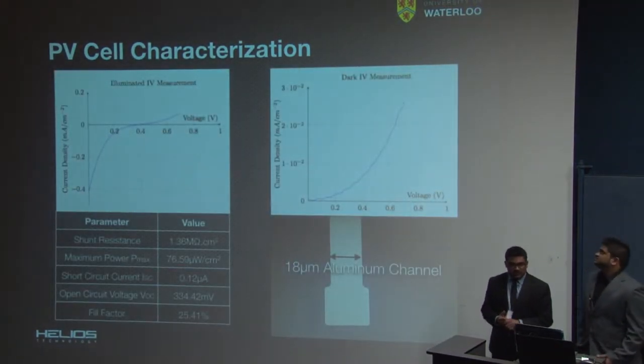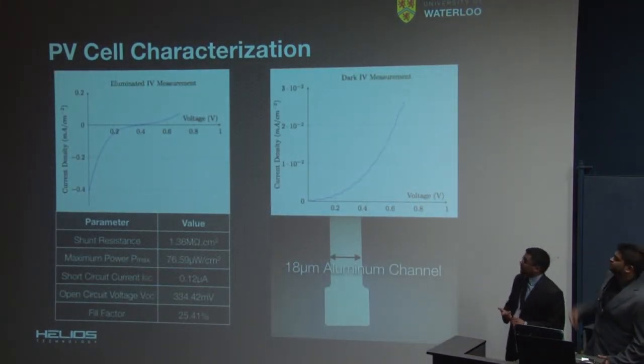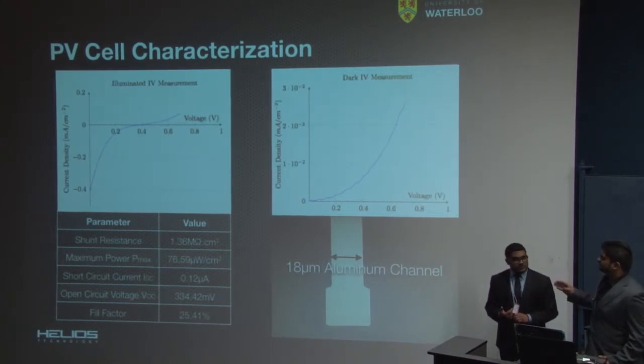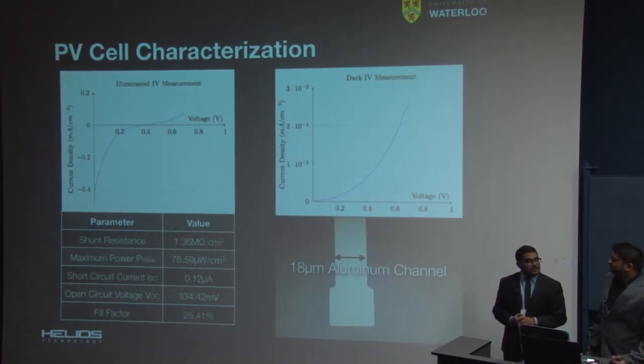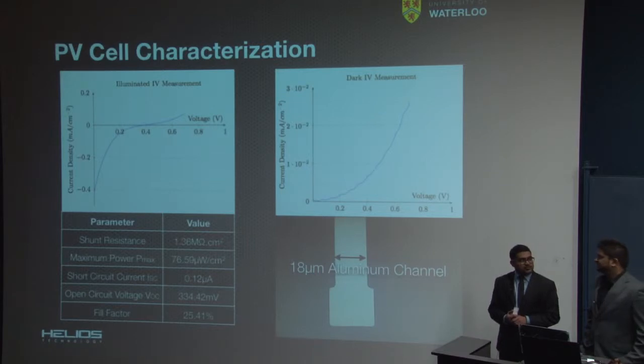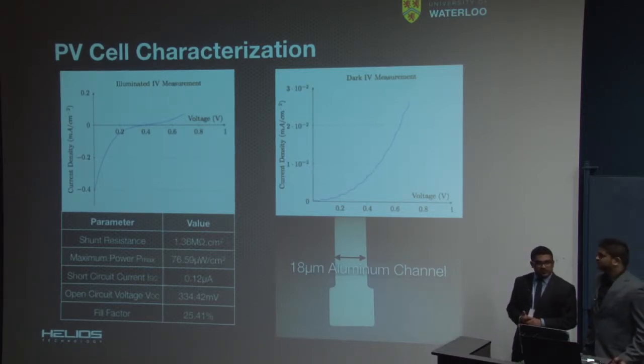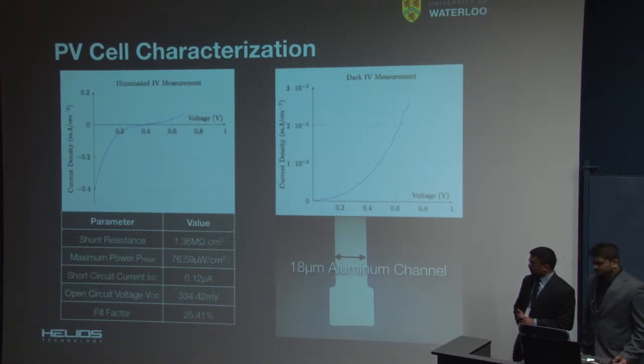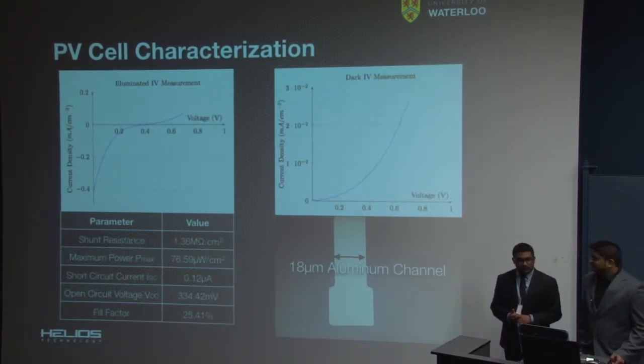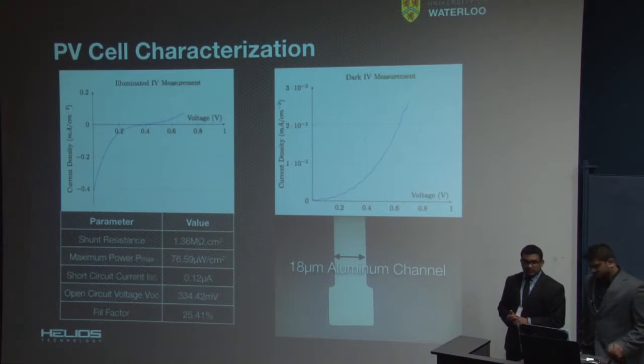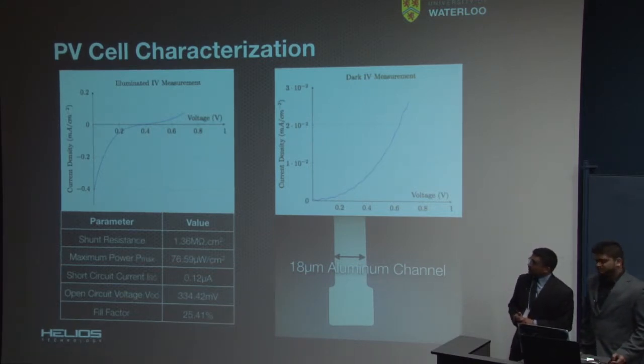Okay, so for our characterization results, our dark IV measurements show just diode characteristics, which essentially means that the contacts were fabricated as intended, and there was good contact between the silicon and the aluminum and the AZO. Our PV cell characterization shows the IV curve that we expected from the solar simulator.